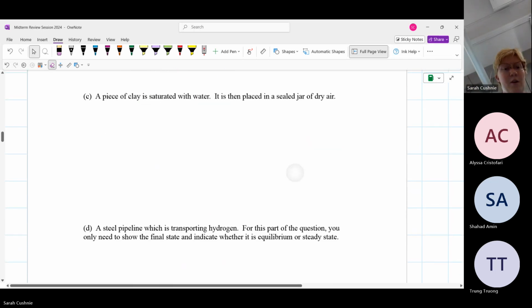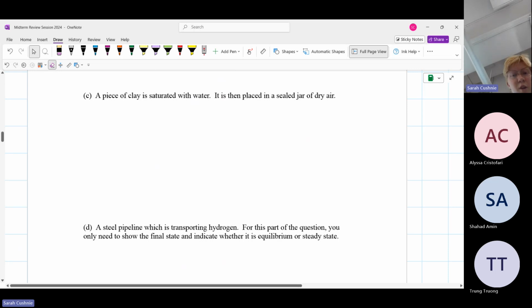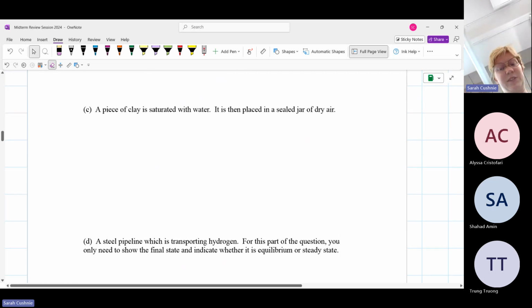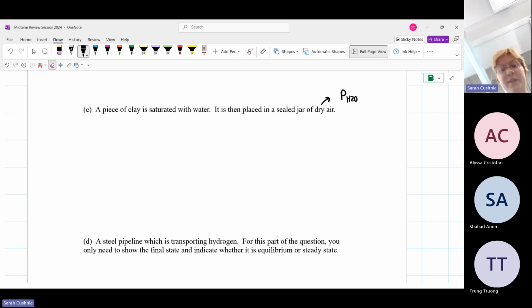Moving on, now we have a piece of clay saturated with water, and then it is placed in a sealed jar of dried air. So this is different than the last situation because now we're in a sealed jar. And what that means is that the concentration of the air will be changing with time. It's no longer going to be constant at 1 atmosphere oxygen, for example. As it diffuses from the solid into the air, we're going to be changing that pressure. We do make the assumption, or at least I wrote down the assumption, that dry air means that the initial pressure of water in the air is equal to 0 at time equal to 0.